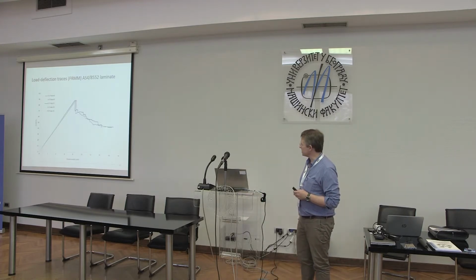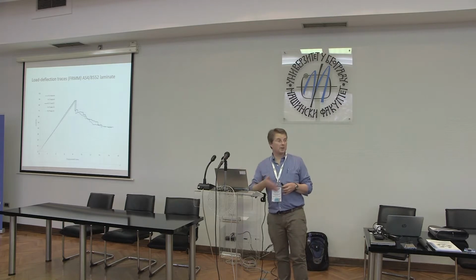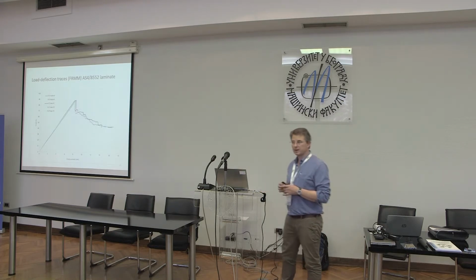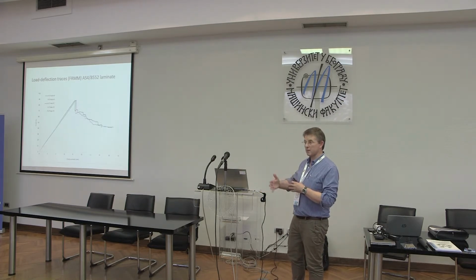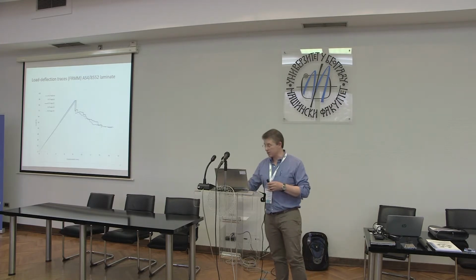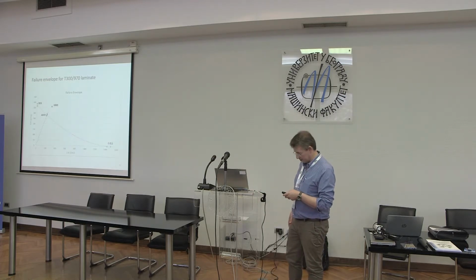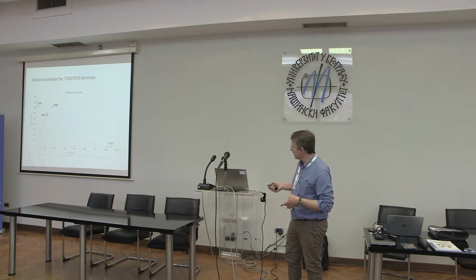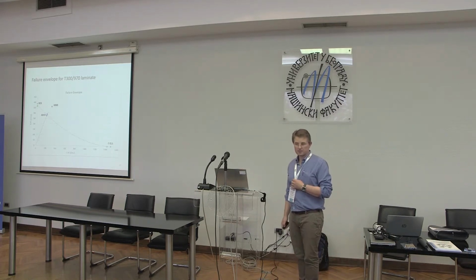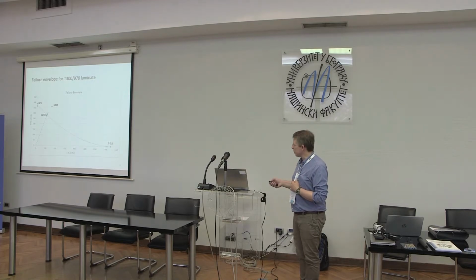And we can also apply the effective crack length approach to that experiment. So it's not always necessary, but if you were going to the more highly mode 2 end of the locus spectrum, it would be necessary. So we get very nice reproducible data, and this is the final result. You can get this sort of curve where we plot the mode 1 value against the mode 2 value, and you generate a 1-2 failure locus. So the mode 1 data falls up here, the mode 2 data falls down here, and our mixed mode value falls there.